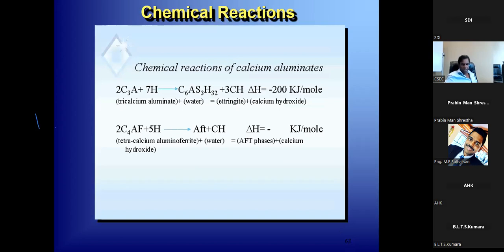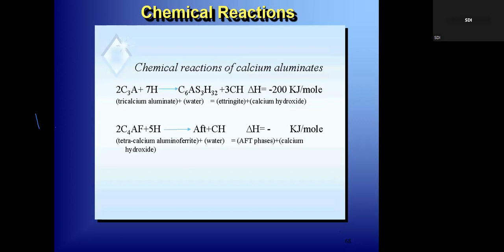There are other chemical reactions in the hydration reaction. C3A also forms what's called ettringite, which is not really good for the durability of the concrete. Again, I will not talk about it in detail. If you're interested, read about delayed ettringite formation, DEF. Ettringite can form later on and expand the concrete and may cause cracking of the concrete. That problem sometimes arises after so many years. So DEF is the word. I will not spend time on it today, but ettringite formation doesn't help the concrete. That comes from the C3A, so you can reduce some of your C3A if you want to make it a bit more durable and if you think there's an ettringite issue.